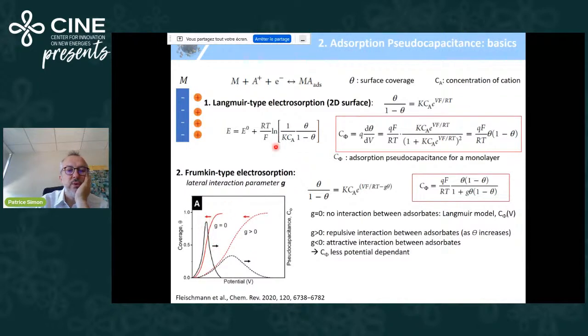For G equal to zero, it means a Langmuir-type model. You have a potential-dependent pseudocapacitance with a very well-marked, pronounced maximum at a given potential. However, when you change the G value, for instance if G is positive, which means repulsive interactions between the adsorbates, so they are forced to get farther from each other, then you smooth the potential dependence of capacitance. So this adsorption pseudocapacitance tends to be less potential dependent when you integrate a positive interaction parameter.